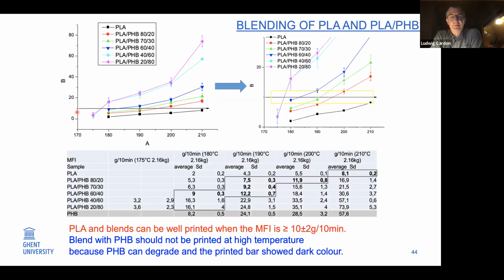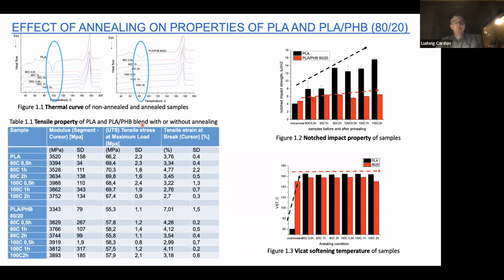So one of the topics we found out is that it's very important in this kind of blending. And so that's a rectangle you can see here in the table. Almost all of them are around between 8 and 10 of melt flow index. So we investigate that also due to the printing, that when you print with a melt flow index reference point based on the pressure and temperature, which you have to correlate afterwards to your viscosity, when you work between 8 and 10, then you have good printing behavior. So that we further investigated.